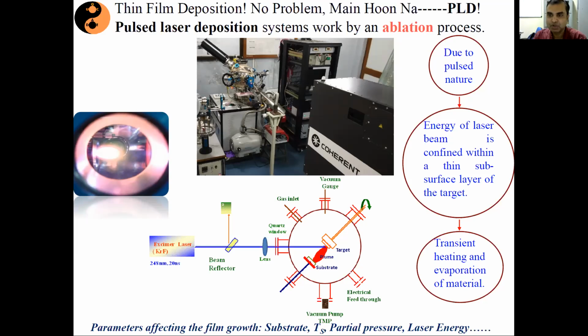With that high power, whatever dielectric bonds are present in the target material are all simultaneously broken. And because of that, the moment the laser beam interacts with the target material, all the elements, all the composition, whatever is present in its vicinity, are all simultaneously ejected. And that is how it preserves the stoichiometry of those compounds which contain more than one element in their composition. So this is a very, very important aspect to grow those materials, to preserve their stoichiometry. So this is as far as pulsed laser deposition is concerned.